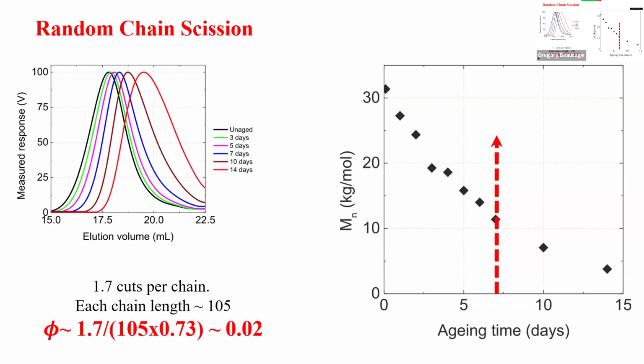So when you make these pieces, it's going to be crystals with lots of amorphous phase coming off. The amorphous phase is going to degrade away slowly. The crystal is going to be left behind. And that's the stuff you're imbibing. I have fear because the shape looks like asbestos. It's crystal. We know crystal is bad. Amorphous is not a problem. Both those factors are why I'm really worried about micro nanoplastics being a health concern.